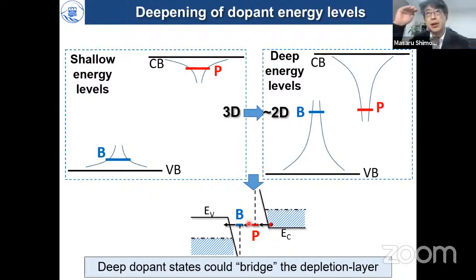My question is, is there any shift after moving the electron toward the boron state, just to keep the position? Yes, it's a kind of a charging energy, because when the electron is inside the phosphorus donor, the potential is lifted up and no other electrons can be entering. And when the electron moves away towards the boron side, then the potential is relaxed again, and it can be allowing again the new electron to come in. So this is specifically, we don't understand yet how this really works, because what I just explained is kind of single electron tunneling. But if it is a resonant tunneling or another type of tunneling through the hybrid phosphorus-boron states, we are still trying to understand that from ab initio simulations.